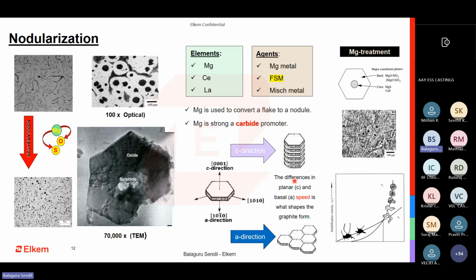Basically, it adjusts the speed at which the C axis and A axis grow. In this chart towards the extreme right, you see the C axis and the A axis here. If the A axis is growing much faster, you typically form a flake. But if the C axis growth is faster, then you form a nodule.